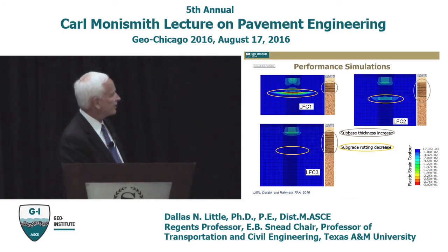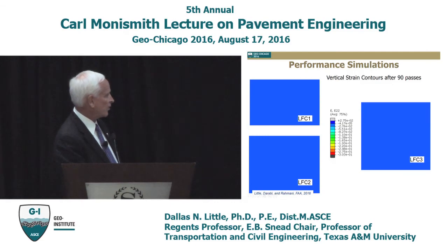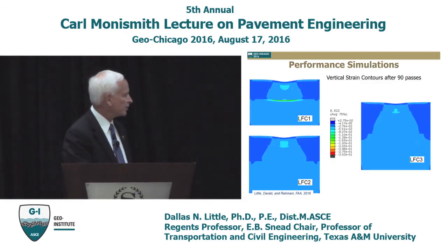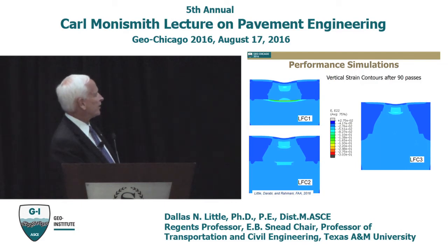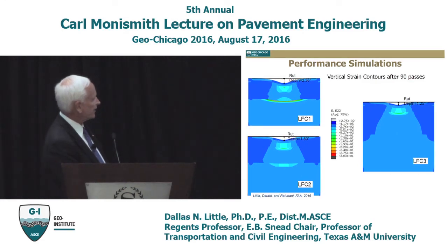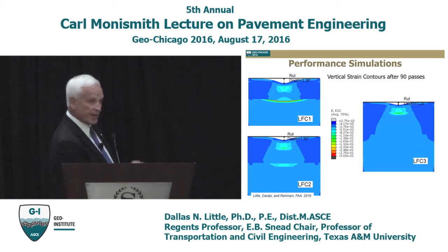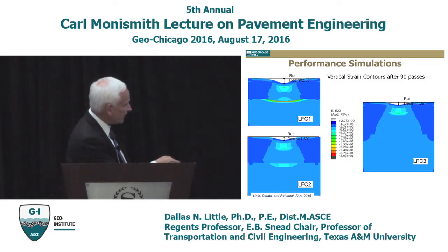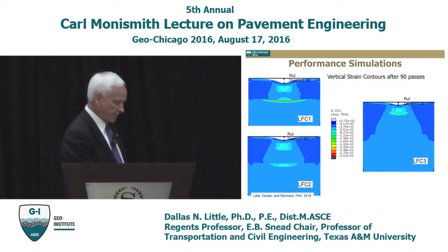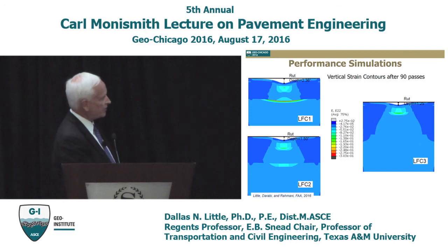But the kicker is not just that, but how much are they different and how well can you predict it. Got a little too much animation here. Could do without all of it. It shows pretty much the same thing. But what we see here is that we were actually able to predict the amount of rutting under a certain level of traffic, which was quite significant due to the subgrade deformation using the Drucker-Prager cap model. Quite different. This is about 2.3 something inches at the top and 1.5, 1.25. So a good bit of difference as the thickness of the subbase increases.